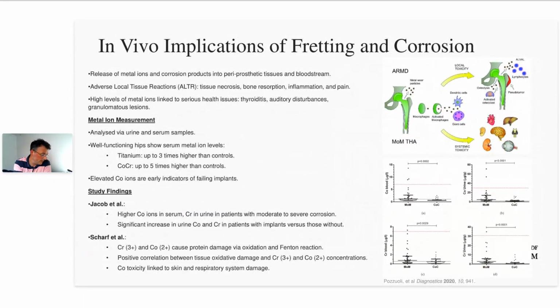So ultimately the reason why we're bothered is because the key implications are not from a structural point of view, but because they're from a biological point of view. And fretting corrosion degradation has ultimately been linked to what we call adverse reaction to metal debris and ultimately failure of the device, which requires some kind of intervention.